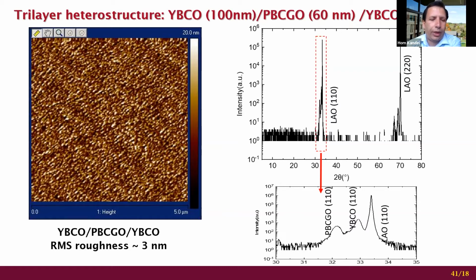The good thing here is our epitaxy, they are perfectly epitaxial, 110 epitaxial, that's what we want. And likewise, the surface morphology is absolutely without any significant cracks. And likewise, the roughness of the surface is about 3 nanometer. Usually we are looking for below 5 nanometer. So for that reason, this is still fine.